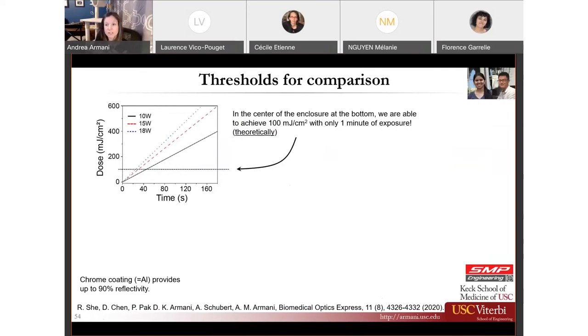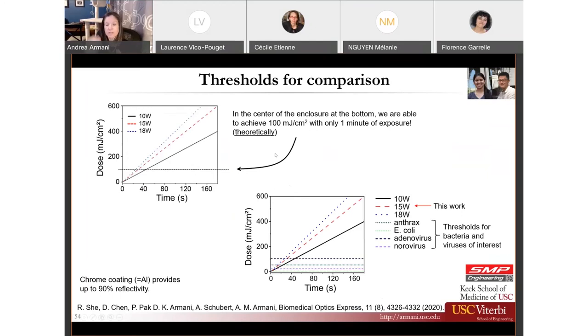For comparison, in our work we used a 15 watt bulb, but on the market you can buy different bulb types, from 10 watt up to 18 watt, at fairly similar prices. Theoretically, you should be able to achieve 100 millijoules per centimeter squared with only 1 minute of exposure. That 1 minute was a really key metric the hospital wanted, because all of their current UVC systems had a 1 minute exposure as the standard operating procedure. They wanted to give their current technicians a system with the same protocol.